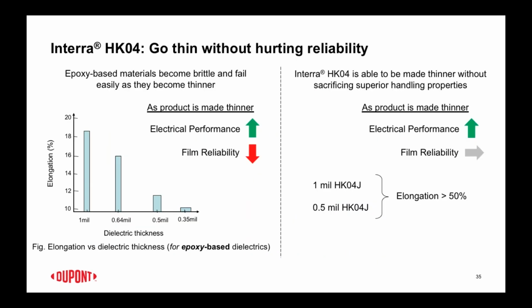And again, the other thing too is that there are some other products on the market, but as they go thinner, they get more brittle, they get hard to handle, and the yields go down typically as well as the reliability. With our material, we've successfully shown that we can go down to 0.5 mil, and we've even got qualification on the 8 micron material. As we're commercializing, we've already got one customer accept it, and so it shows that because these films are inherently so strong electrically, mechanically, and thermally, you don't pay a penalty for going thinner.